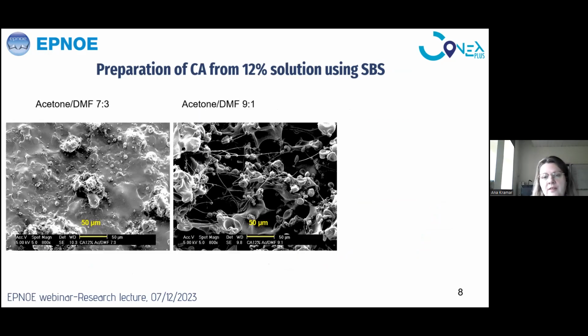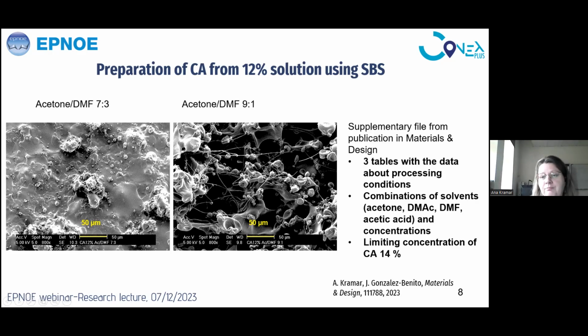So in the beginning, we found the limiting concentrations were actually 12 and 14% of cellulose acetate solution. And here you can see this versatility that I was speaking about in solution blow spinning: when we use a certain composition of a solution, when we dissolve our polymer in acetone and dimethylformamide in 70-30% ratio, we obtain a film. And if we decrease the ratio of dimethylformamide by only 20%, we obtain fibrous morphology. However, these fibers were not without beads. We had a lot of material imperfections, so to say.